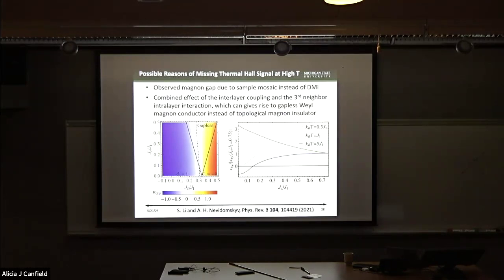In this theoretical paper, they found that the thermal Hall conductivity in chromium triiodide is very sensitive to both the interlayer interaction and the third-neighbor intralayer interaction. From this phase diagram, we can see that the thermal Hall conductivity changes sign from negative to positive. And it turns out that in this calculation, within some parameters, the magnetic state of the system could undergo a topological phase transition from a topological magnon insulator to Weyl magnons.